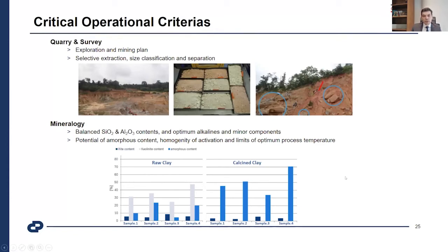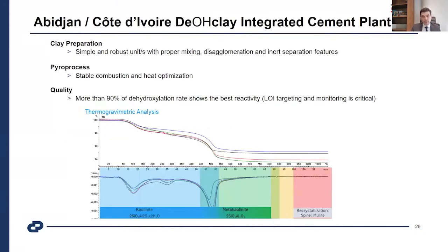You have to get as much amorphous content as possible to get the highest reactivity with the optimum process conditions. After a higher temperature, as you know, on one side it goes to crystals that are non-reactive and hard to grind: mullite, cristobalite, and other things. The other part is the non-dehydroxylated portion. It also causes quality problems on the cement side.